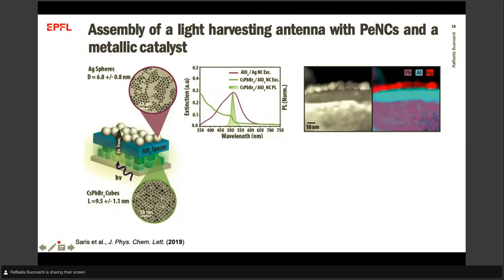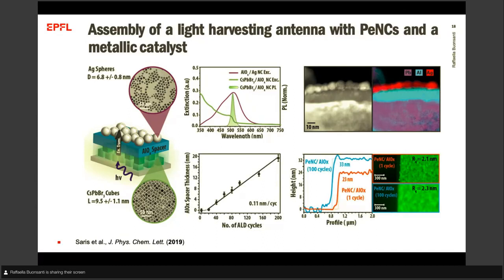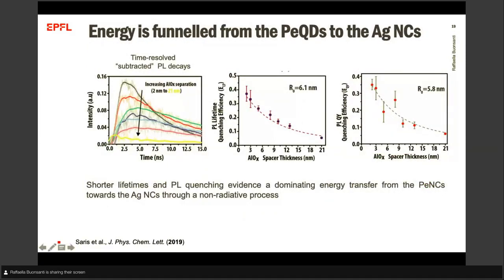The optical properties of the perovskite nanocrystals and the silver nanoparticles match well the requirement for energy transfer. The two layers are well separated, so they cannot react with each other. And we were able to tune with the ALD the thickness of this alumina layer from 2 nanometers up to 20 nanometers in order to study the distance-dependent properties. What we found is that as the distance decreases, we have an increase of the PL lifetime quenching efficiency and also an increase of the PL quantum yield quenching efficiency. The two together indicate that the dominating mechanism is energy transfer from the perovskite nanocrystals to the silver through a non-radiative process.